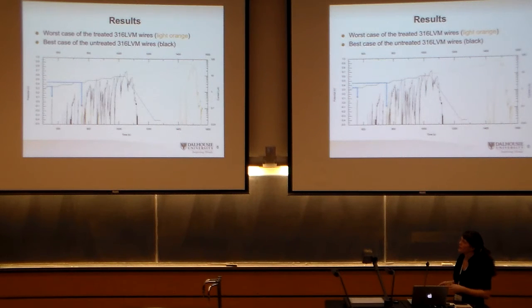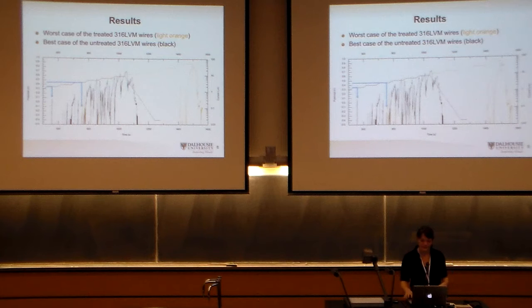So first event for the untreated wire occurred at 350 millivolts. And then continued pitting, reaching greater than 10 microamps in size by 600 millivolts, by which point the surface has been completely destroyed by pitting corrosion. You can also see in light orange our treated wire started pitting around 450 millivolts, and there were only a few very small events, and then nothing occurred until 800 millivolts, at which point non-localized pitting occurred.